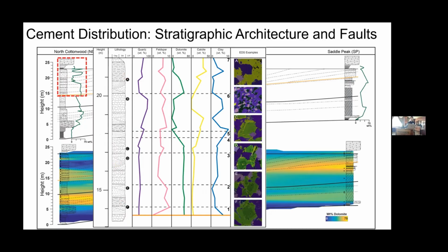So what I want you to notice is that in these bottom 3 clinoforms, we kind of see the same morphology and abundance of dolomite and calcite from top to bottom. There's a little bit more calcite toward the top, but generally things look the same, both from an abundance standpoint and from a morphology standpoint. As we move up to these clinoforms 5 and 6, things start to change pretty drastically. Particularly looking at this EDS view B, there's no dolomite in these samples whatsoever, or very little. And there's this well-preserved molded porosity after feldspar that we don't really see anywhere else in the section, and it's kind of limited to this clinoform.